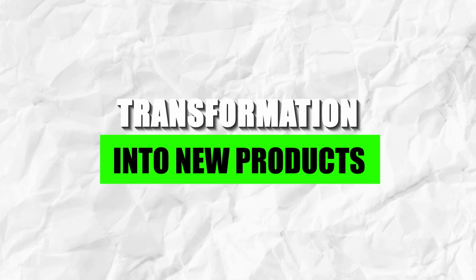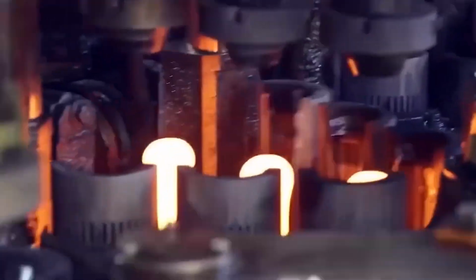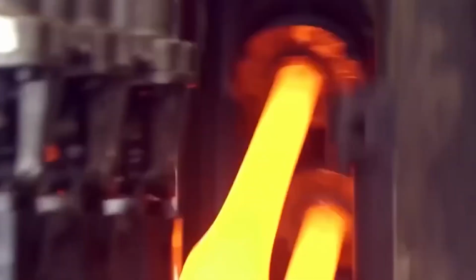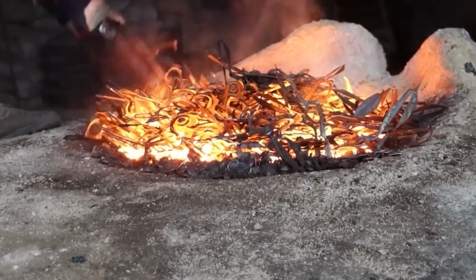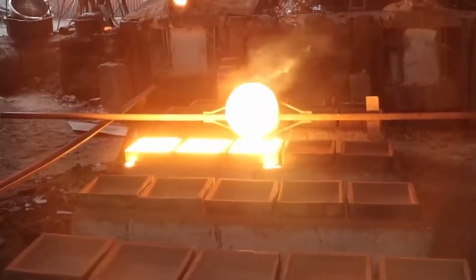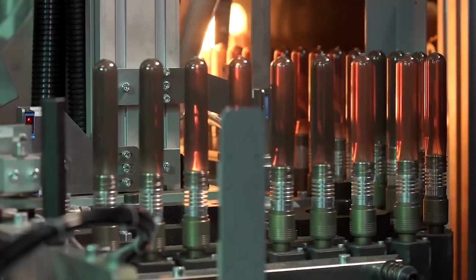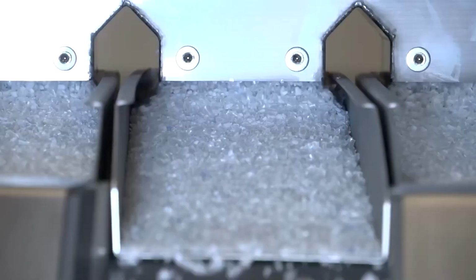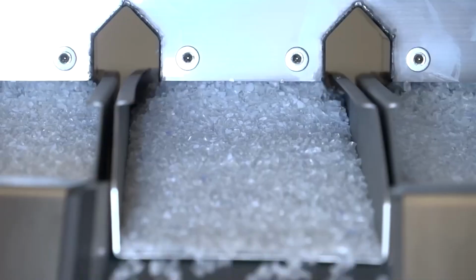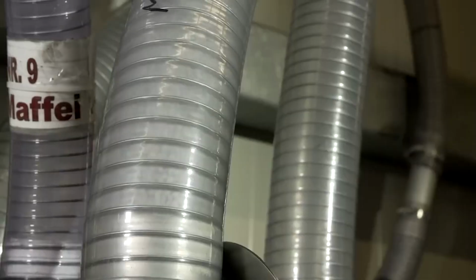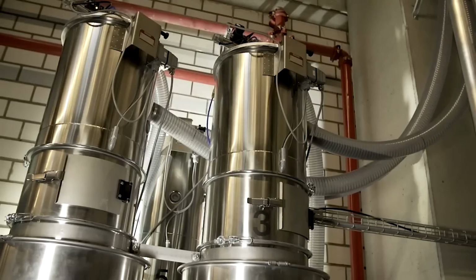Transformation into new products. The sorted flakes enter sealed heating chambers at 520 degrees Fahrenheit. Multi-stage vacuum systems remove residual moisture, air bubbles, and contaminants, leaving pure molten plastic with stable viscosity. This molten plastic undergoes underwater pelletizing. High-pressure cold water rapidly cools and shapes it into perfectly round pellets, free of cracks, voids, or trapped gases, meeting